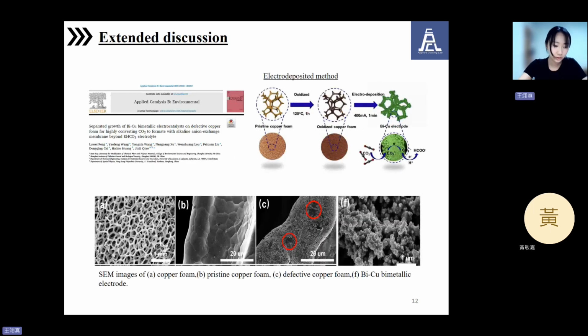Then we read the other paper. In this study, the authors present another approach for fabricating copper-bismuth bimetallic electrodes, but instead of using MOF, this directly deposits copper and bismuth onto thermally oxidized copper foam using an electrochemical co-deposition method.